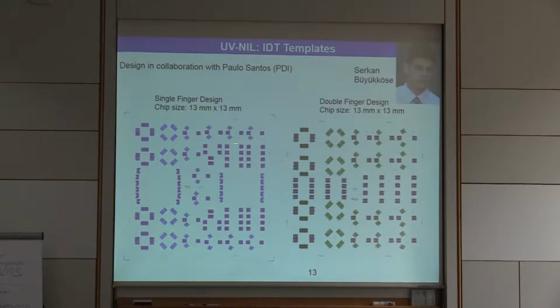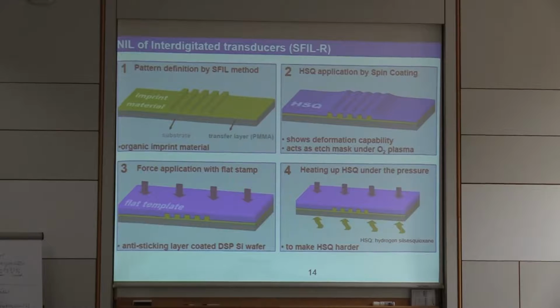You see we have all kinds of different geometries allowing for all kinds of experiments. So we have used a slightly different technique from the standard imprint lithography, the so-called reverse process of the step and flash imprint lithography. The first step is the same, so we imprint in imprint material, which is an organic layer, in this case a polymer again, but then we spin on another organic-based silicon-containing material called HSQ, hydrogen silsesquioxane. I prefer saying HSQ, which is used as a planarization layer, and will also result in an inversion of the pattern.